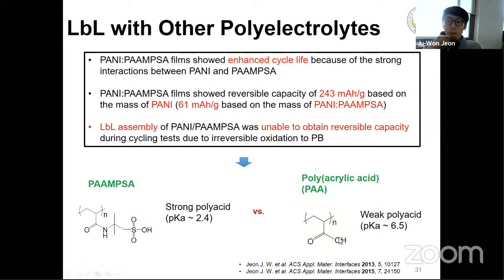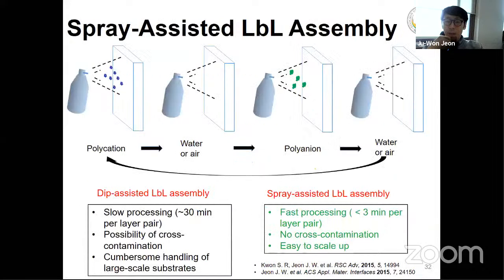polyelectrolyte, like polyacrylic acid, PAA, which has a higher pKa than the PAAMPSA. So its pKa is around 6.5. And in this case, instead of the traditional conventional dip assisted layer-by-layer assembly, we performed the spray assisted layer-by-layer assembly because of these advantages.